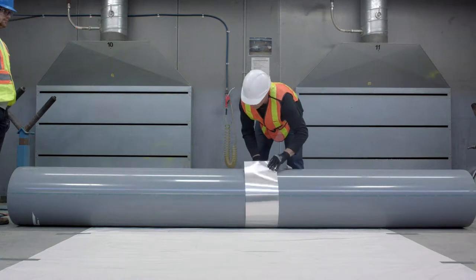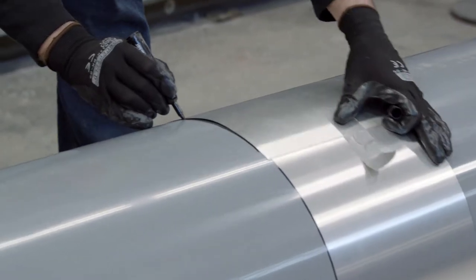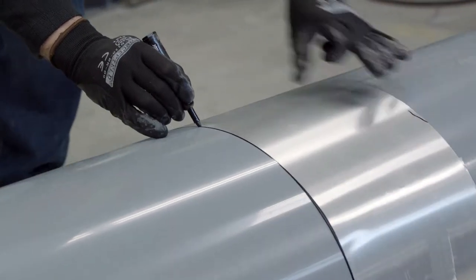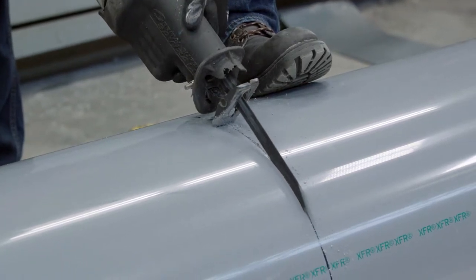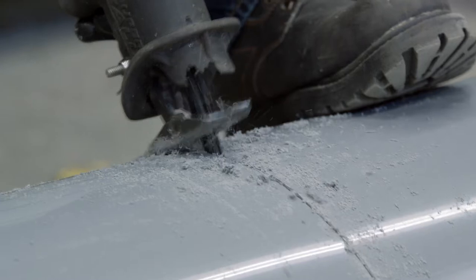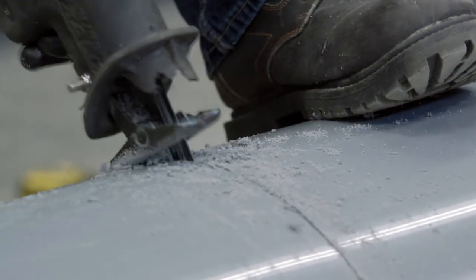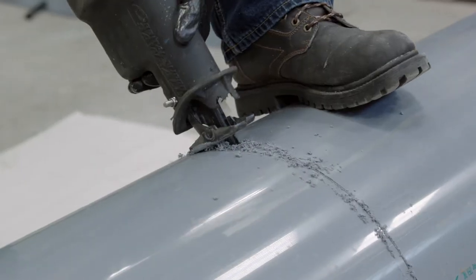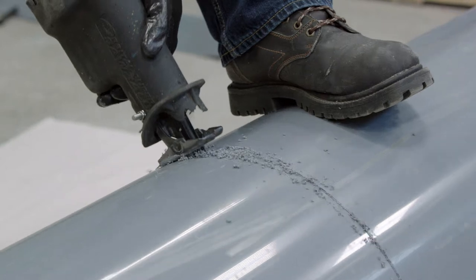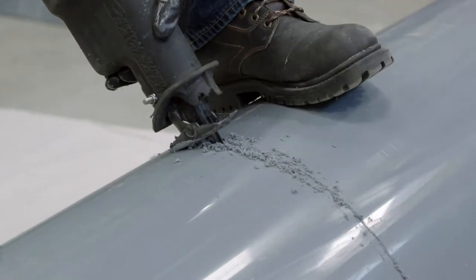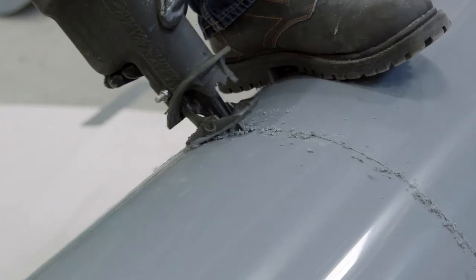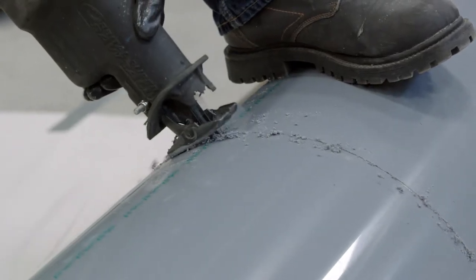Begin with drawing in a square circumferential line by using a flexible straight edge. Pipe can easily be cut with a fine-toothed chop saw. A reciprocating saw may also be used provided the operator cuts along the square circumferential line. Tools used to cut pipe must be designed for plastic piping and must be in good condition. If there is any indication of pipe damage or evidence of pipe end cracking, cut off at least two inches beyond any visible crack.